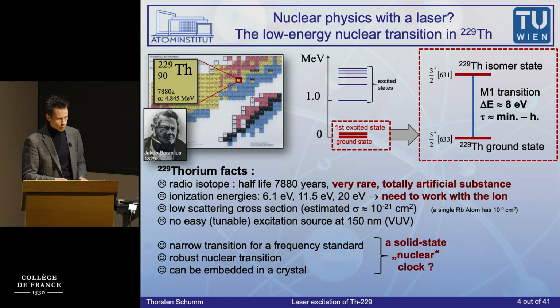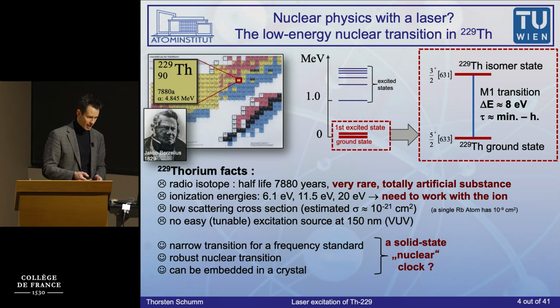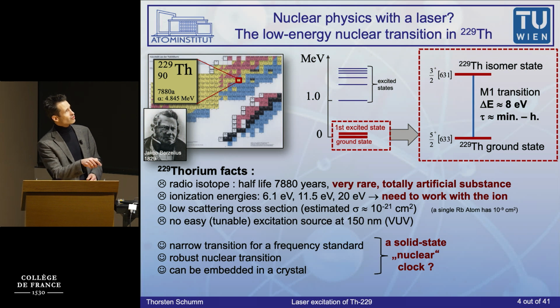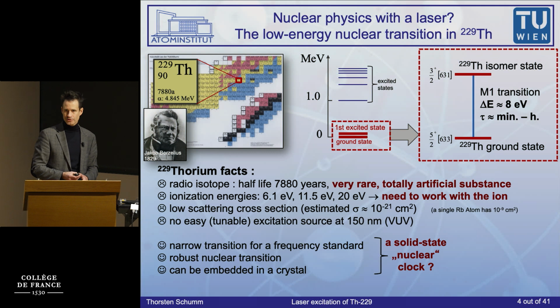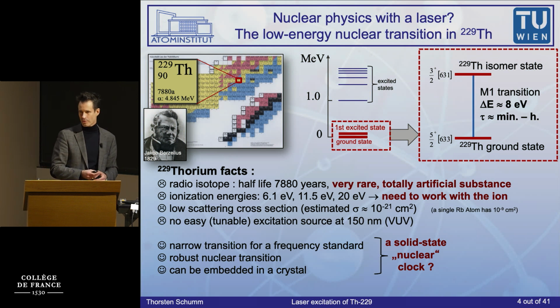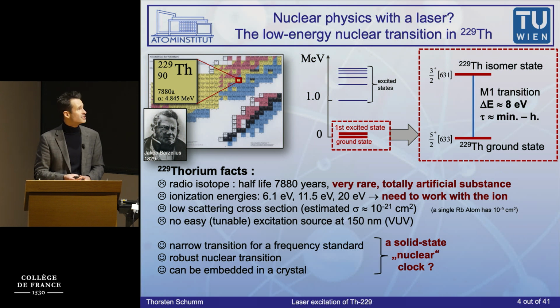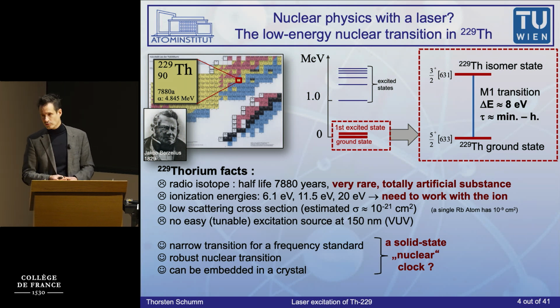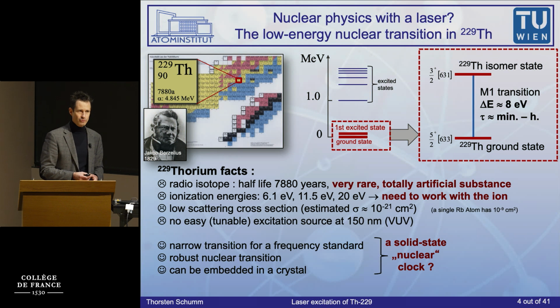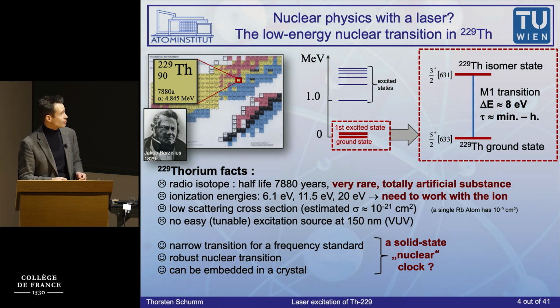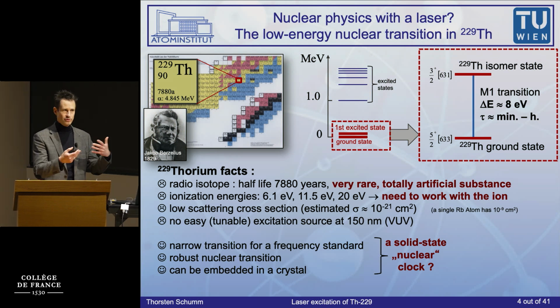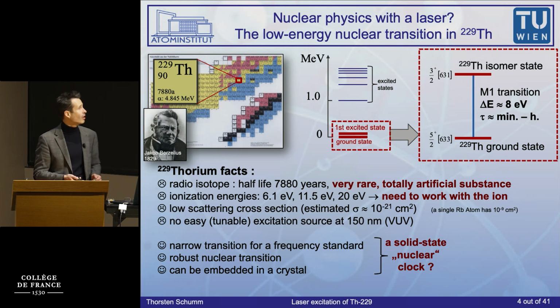Good, but there are a few pros for why one should still maybe try. The first one I already mentioned: it's essentially 1 over this quantity here, which is the spectroscopic line width. If I have a two-level system that lives for a time x, usually 1 over x is the Fourier-limited line width. You can calculate yourself what the line width is of an excited state that lives for minutes to hours. It is very, very narrow, and this is why people are excited about using this as a reference transition for a new type of clock, which would then be a nuclear clock because it's relying on a nuclear transition.